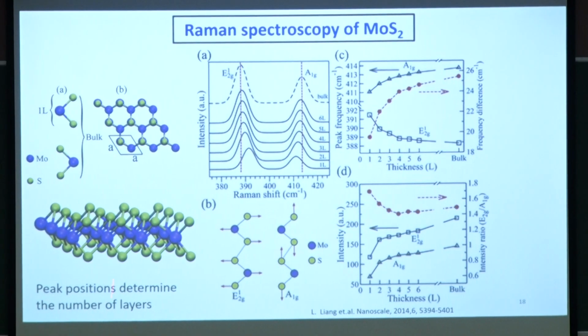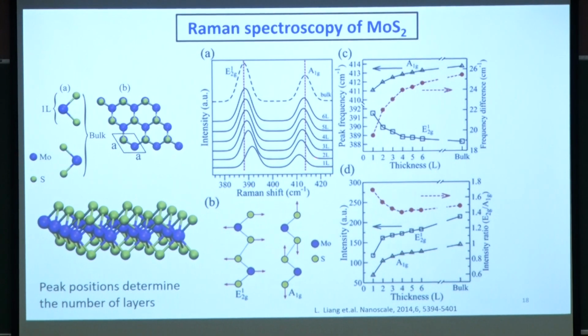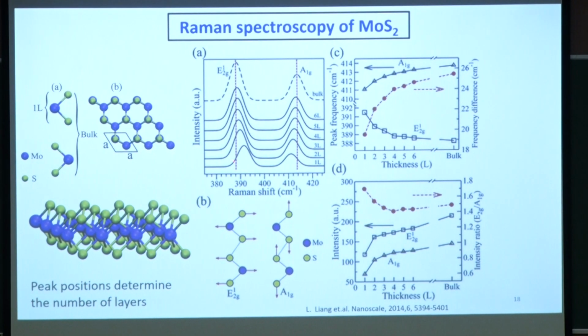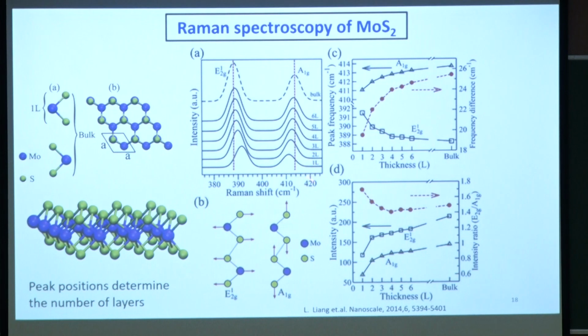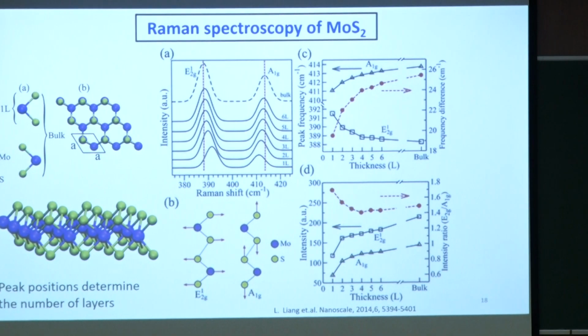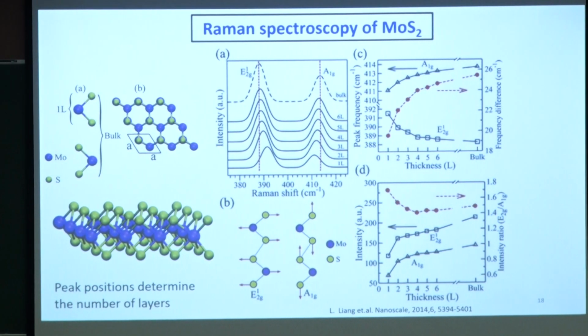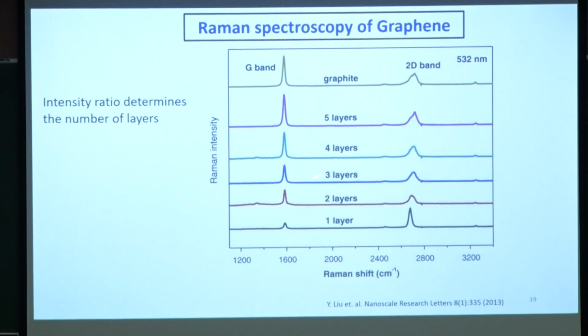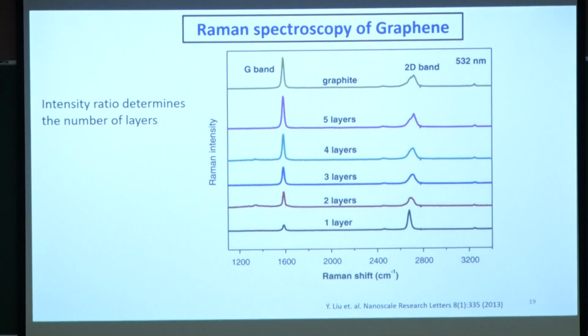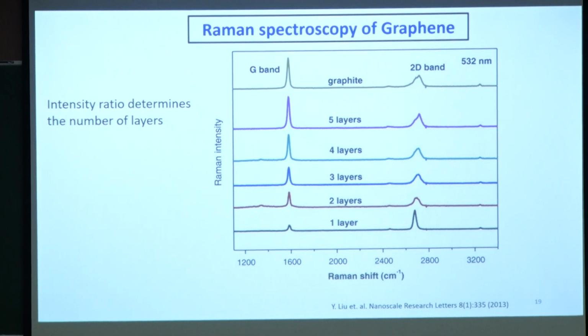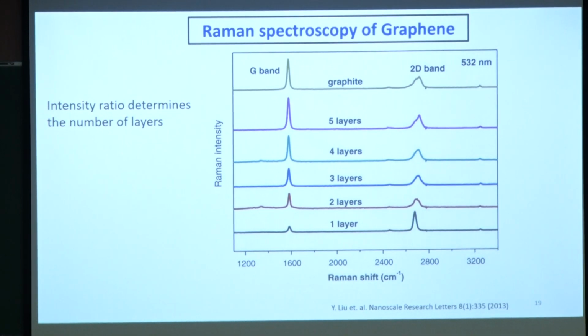So in the case of MoS2, you can see that if you go from one layer to bulk, the peak position is changing. We really do not care about the relative intensity in this case. But if you go to graphene, the peak position does not change. What changes is the intensity, and just by looking at the intensity, you can tell whether it is a monolayer, bilayer, trilayer, or four layer. It is very accurate. It is amazingly accurate.